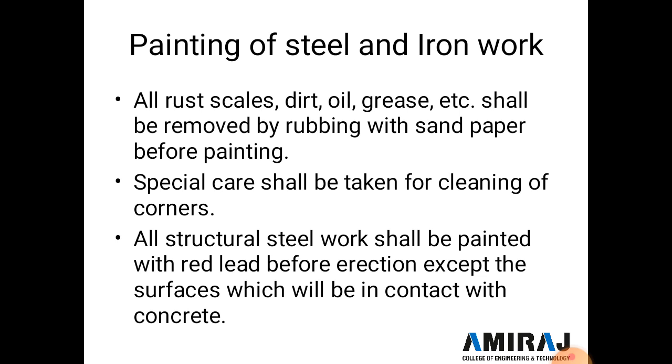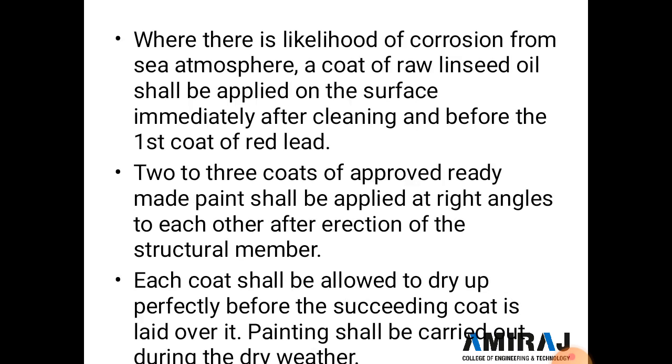Where there is likelihood of corrosion from sea atmosphere, a coat of raw linseed oil shall be applied on the surface immediately after cleaning, and before the first coat of red lead is applied. Two to three coats of approved ready-made paint shall be applied at right angles to each other after erection of the structural member, and each coat shall be allowed to dry perfectly before the succeeding coat is laid over it, and painting shall be carried out during dry weather.